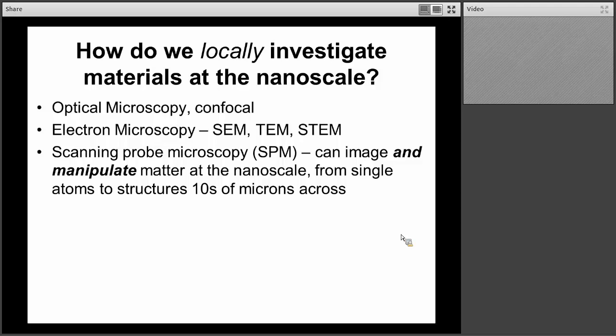So how do we actually investigate materials at the nanometer scale? It started off with optical microscopy, which has a resolution on the order of half a micron. If you're clever and use confocal microscopy, you can get it down to about 100 to 150 nanometers. You can access smaller length scales on the atomic scale by electron microscopy — SEM, TEM, and STEM — which are a very powerful family of techniques, but they require quite special sample preparation. You can't look at samples in vitro or in a liquid environment, so they're not good for biological samples, and they are just microscopy techniques — it's quite difficult to do anything apart from just looking at things. That's where scanning probe microscopy is so powerful.